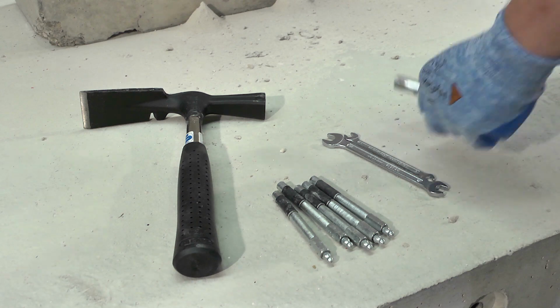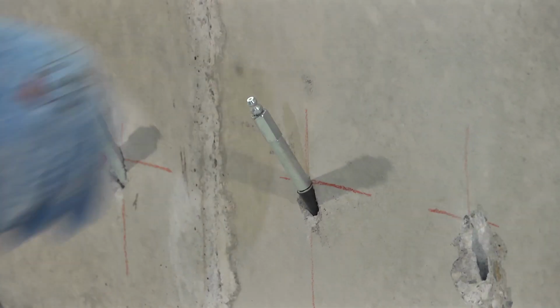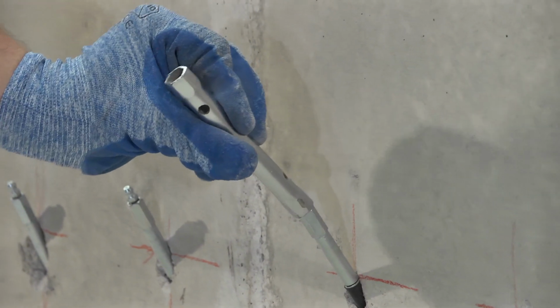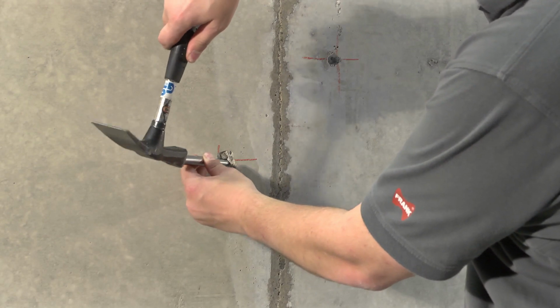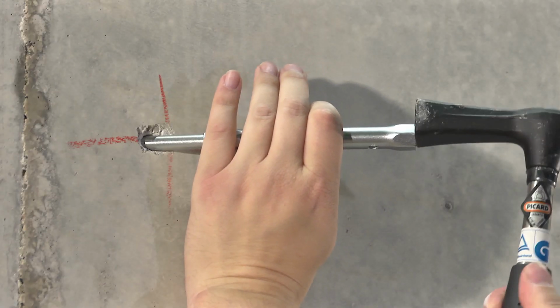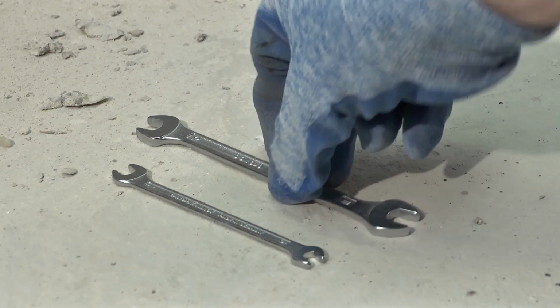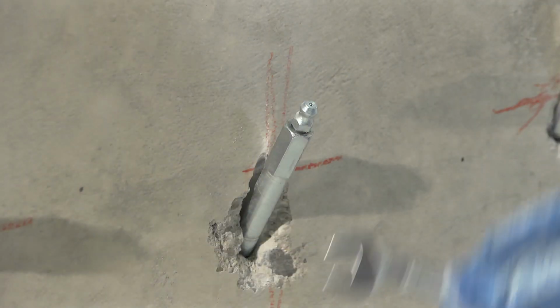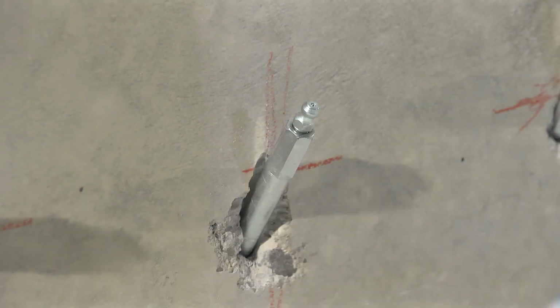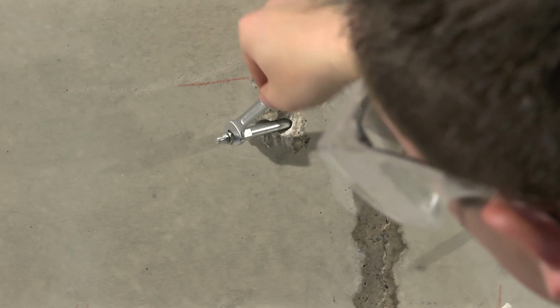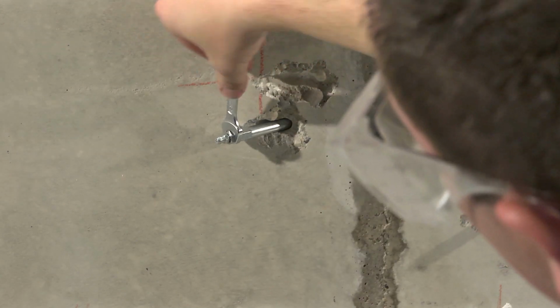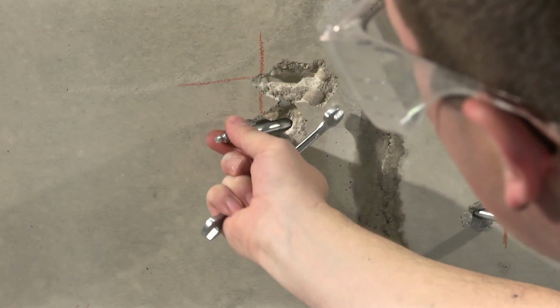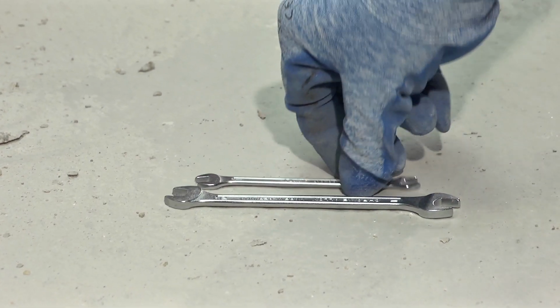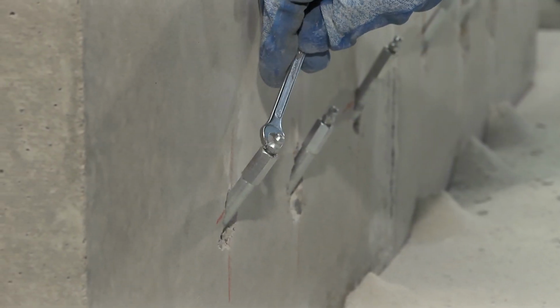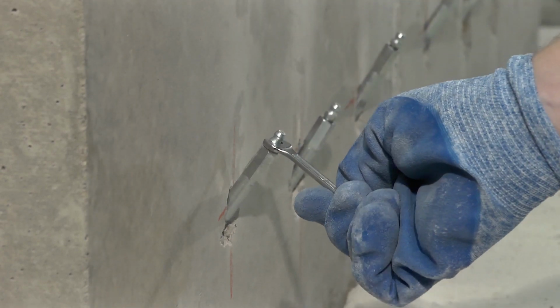After cleaning, insert the packers into the drilled holes. Do not use a hammer to tap the conical heads, as this may damage the delicate valve tips. Preferably use a box spanner to tap the packers into the drilled holes. All packers must be tightened as required after placement. For all packers, it is absolutely necessary to check for adequate torque. Avoid excessive tightening in order to prevent packer shear off. Prior to injection, recheck that each packer has been properly installed.